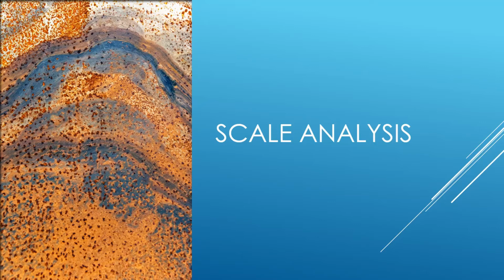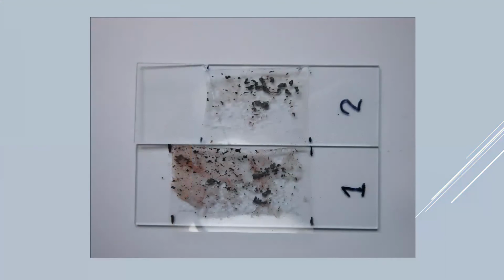And the other thing that happens with the cellulose acetate is that if you've got a scale on a surface that's very thin, there's not much there, you can wet the cellulose acetate, apply it to the surface and strip it off like this. And that's what you would get: you would have the corrosion product on that cellulose acetate, and now it's mounted on that slide. Now I can go off and do energy dispersive spectroscopy on it. If the cellulose acetate is thin enough, I can also grind this up and do X-ray diffraction on it.